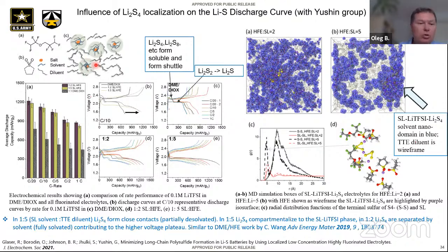So the Yushin group has looked at two concentrations, 1 to 2 and 1 to 5. 1 stands for sulfolane, 2 or 5 for diluent, putting in much more diluent, 5 times more than sulfolane in this system, while also keeping a relatively low concentration of lithium TFSI. What happens is that in the system with just twice as much diluent, there are still 2 plateaus showing different rates. And once a very large amount of diluent is introduced in a system, there is only 1 plateau. The second plateau shrinks to a very small size. And that does help with capacity retention, coulombic efficiencies, and prevention of shuttle.